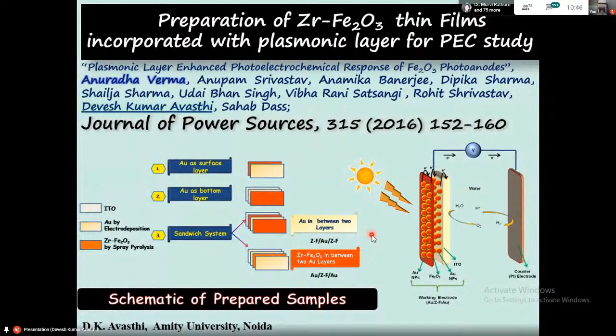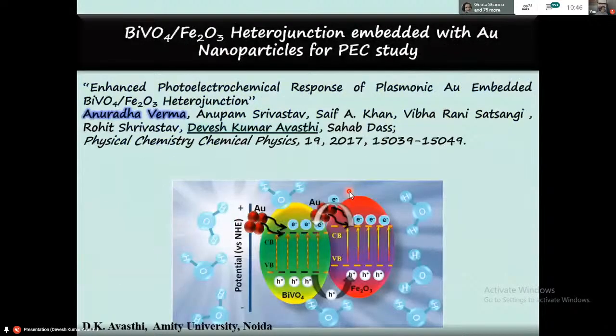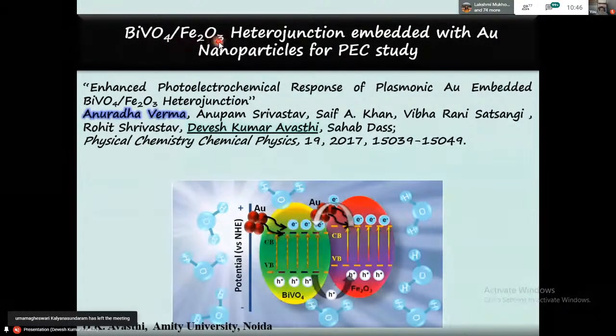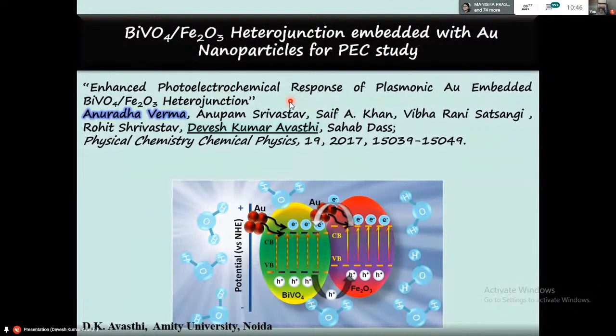or a combination of all, there is always an increase in hydrogen production whenever we put in a plasmonic layer, which was gold in this case. Next, what was tried was bismuth vanadate, and iron oxide is also one of the popular materials for photoelectrochemical response. We mixed plasmonic material inside there. That means nanoparticles of gold were mixed inside here and inside here. In this case also, we had increased production of hydrogen. And this is a schematic shown over here. One can read more details in this paper.